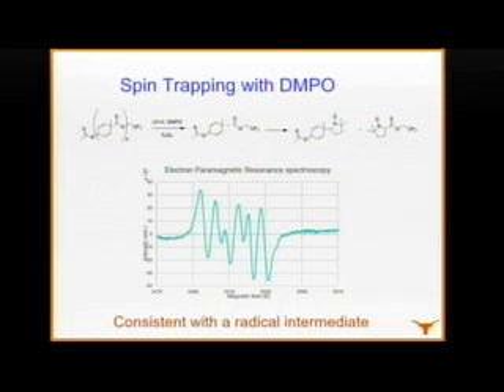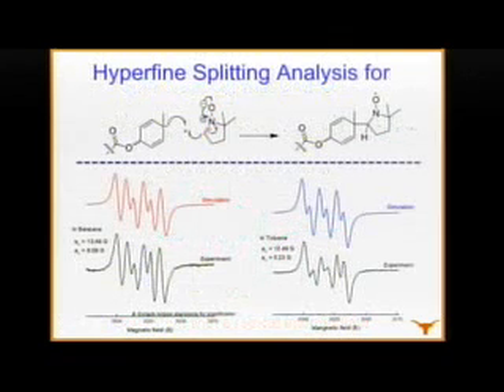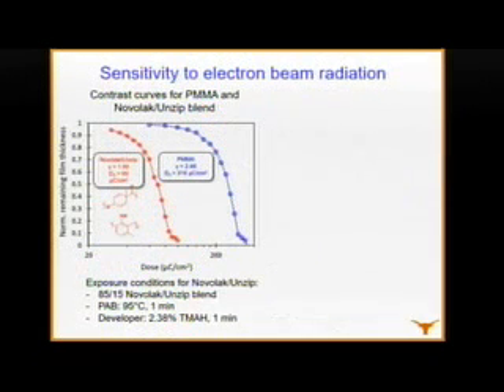But no, the student was better than I am, and he decided to look more closely. And he found that it's possible to actually find free simulators for ESR spectroscopy, and he simulated this structure, and good grief, it looks almost fake. So I think we have a fair level of confidence that it is a free radical reaction and that this intermediate is being generated, and this whole unzipping thing is going on from radical intermediates. So anyway, made a photoresist of the material.